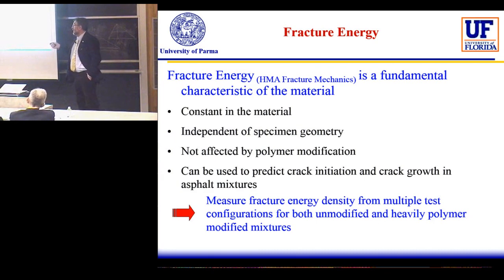We were able to show that this approach was independent from the specimen geometry and not affected by the polymer modification. For those who are not in the field of asphalt pavement, the bitumen, the black part of the asphalt, could be natural bitumen or could be the so-called polymer modified bitumen. It is a technique that allows adding polymer inside the bitumen to improve the elastic behavior of the material and also its strength.